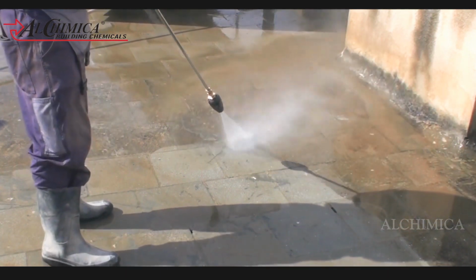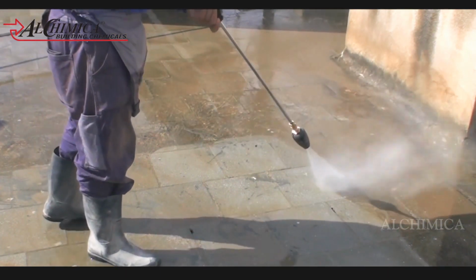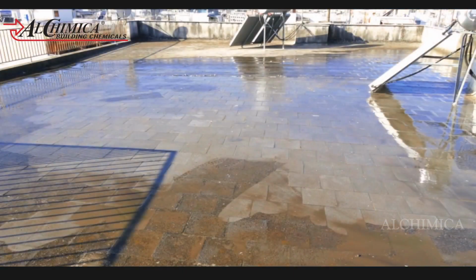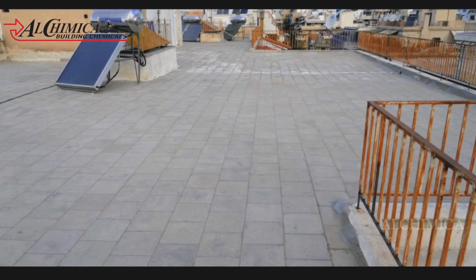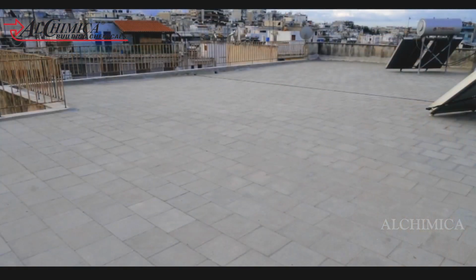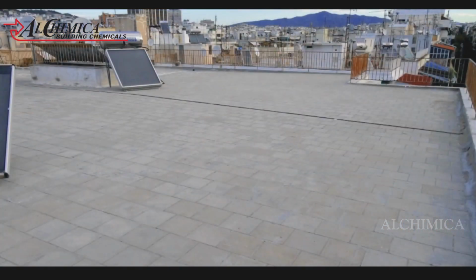Then the prepared surface is applied with Microsealer 50, a polyurethane-based low viscous primer. Material inside the pail has to be mixed well with a slow speed stirrer, 300 rpm. This is applied with a roller brush or by airless spray machine.